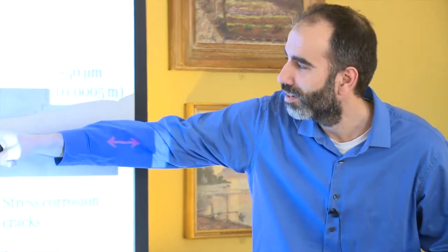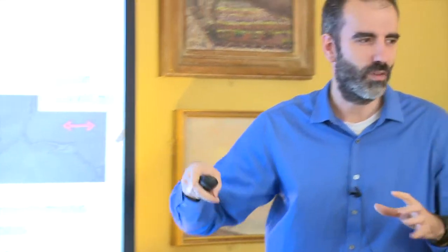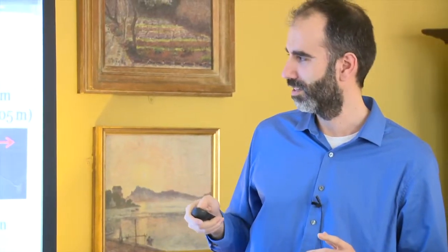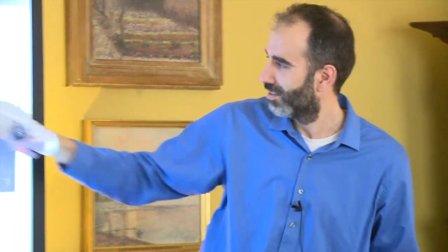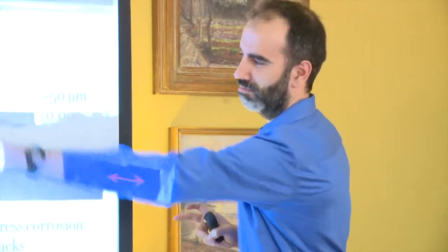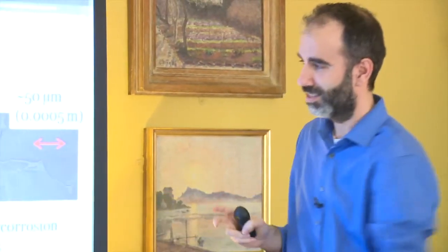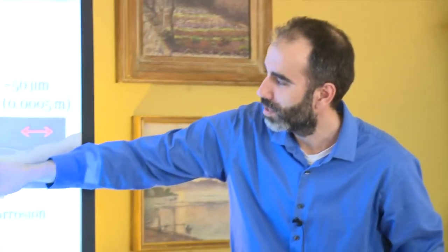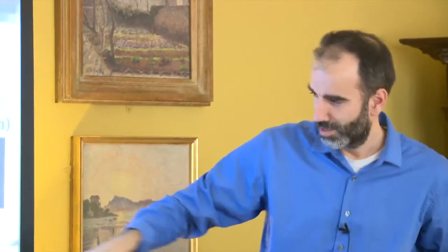That will be a 10,000th of a meter, right? So for you to start getting a feeling, this is the type of cracks that are going to give trouble in a structure like this. This will be roughly the size of a hair. And this crack is, as I said before, 100 or 200 times thinner than a hair. All the action is not going to happen here because that has already fractured and opened a little bit more. All the action happens there at the crack tip. That's where it's growing. So for that, you need electron microscopy, which is what I'm showing there.